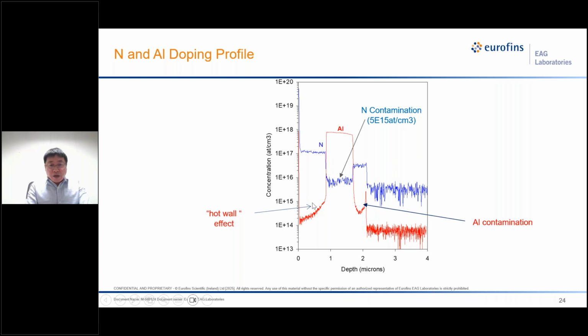Another thing I want to point out is the hot wall effect. This is due to the source being turned off, but the source is still hot, so it will keep doping in the background. This is only observed in the old process, but not now.